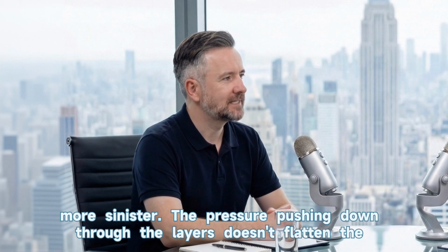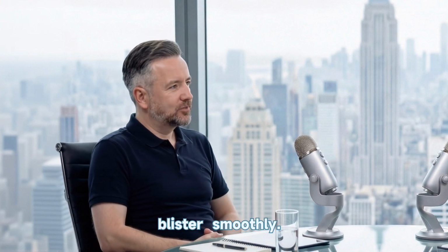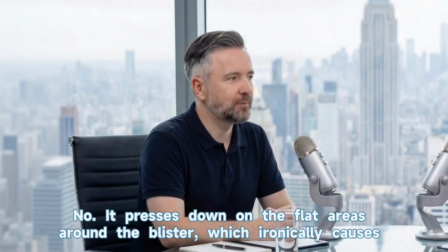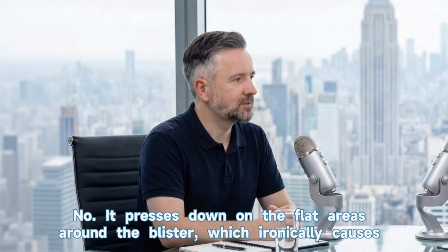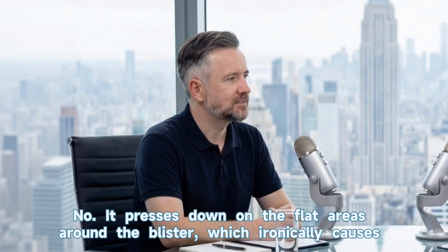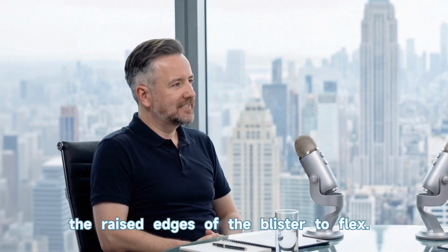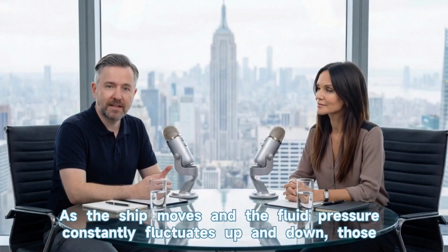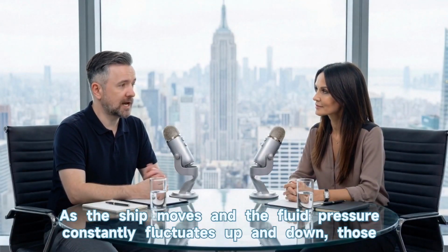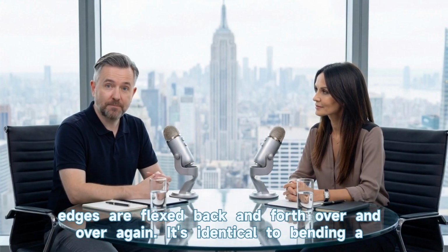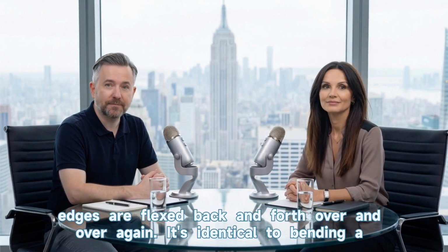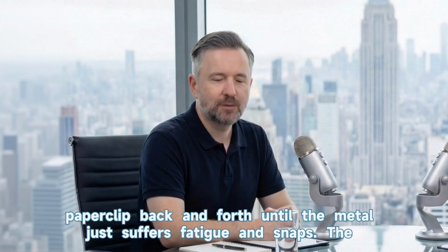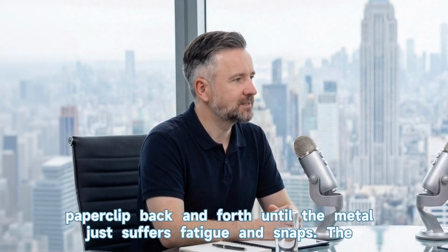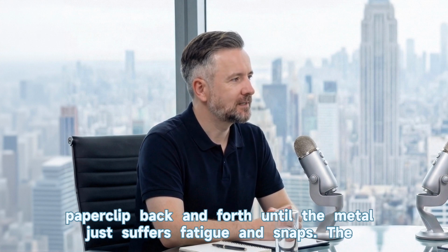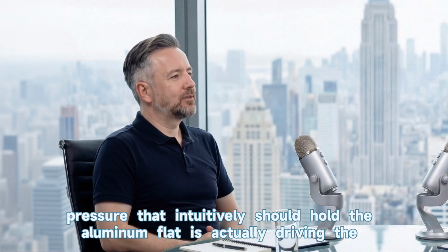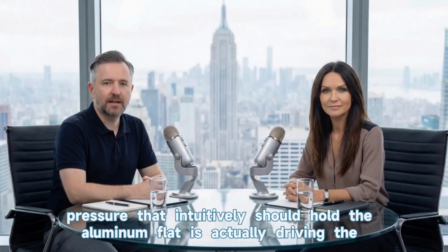The pressure pushing down through the layers doesn't flatten the blister smoothly. It doesn't. No. It presses down on the flat areas around the blister, which ironically causes the raised edges of the blister to flex. Ah, I see. As the ship moves and the fluid pressure constantly fluctuates up and down, those edges are flexed back and forth over and over again. It's identical to bending a paperclip back and forth until the metal just suffers fatigue and snaps. The pressure that intuitively should hold the aluminum flat is actually driving the fatigue crack.